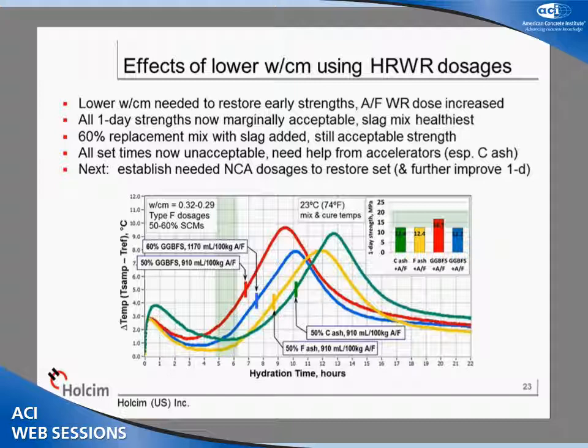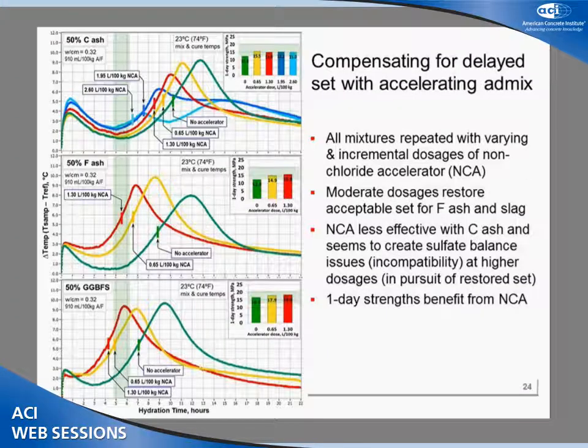Unfortunately, the chemical admixture use in this case has now retarded our mixture to a point that the setting times are no longer, any of them, in the target band. So we're going to need to accelerate this mixture for adequate performance in flat work finishing. We do that with accelerating chemical admixtures. We're going to do it with non-chloride accelerating admixtures in this case. And